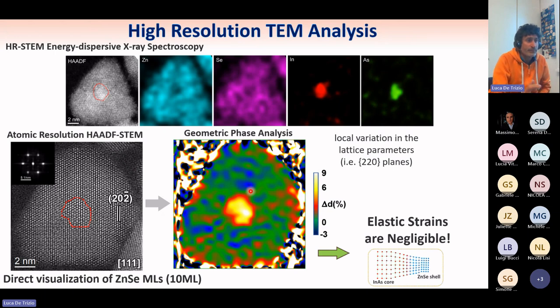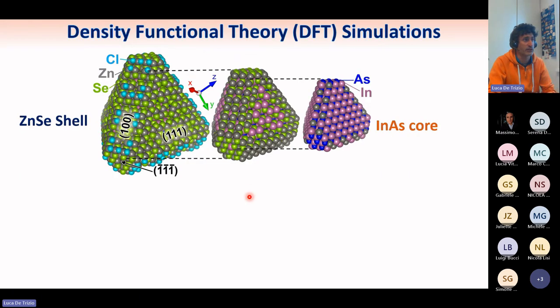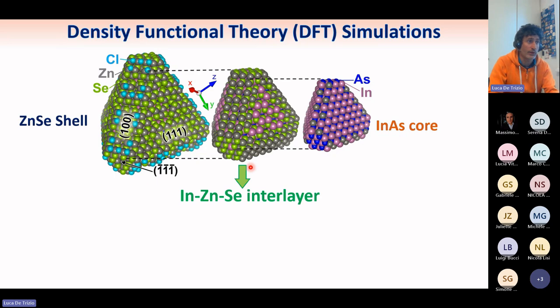And to investigate why there is actually no strain in this structure, we performed calculations coupled with empirical analysis. And what we found is that the reason why we don't have such stress in our structure is that in our conditions, we are forming this interlayer, having lattice parameter in between those of the shell and those of the core.